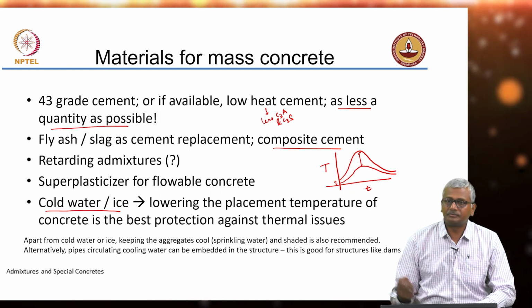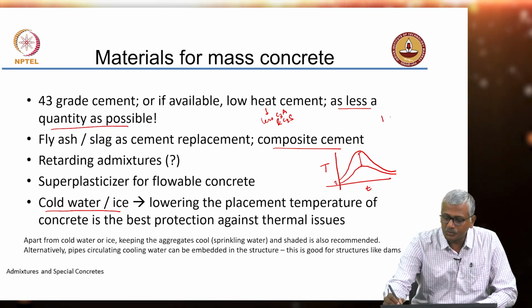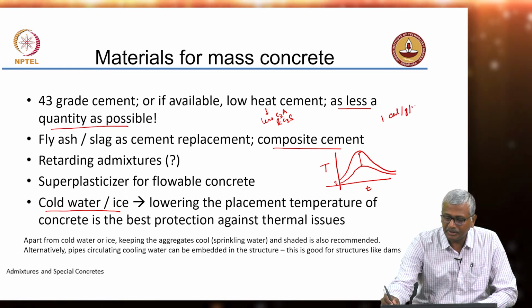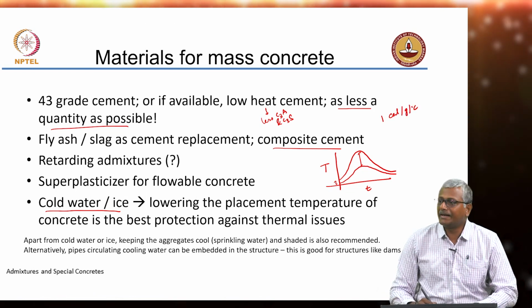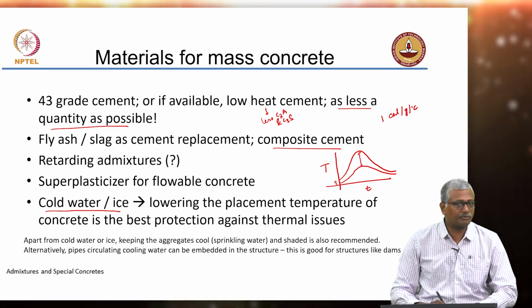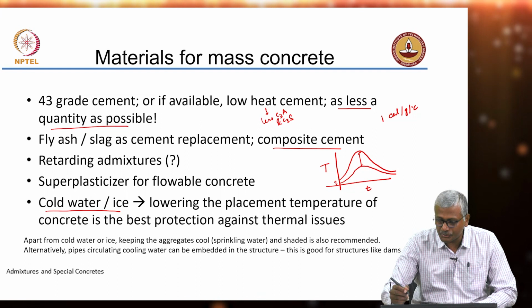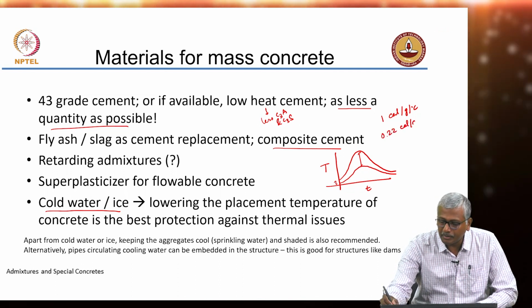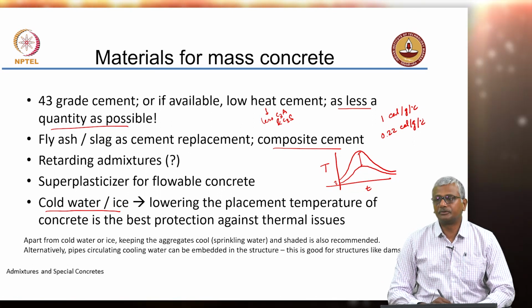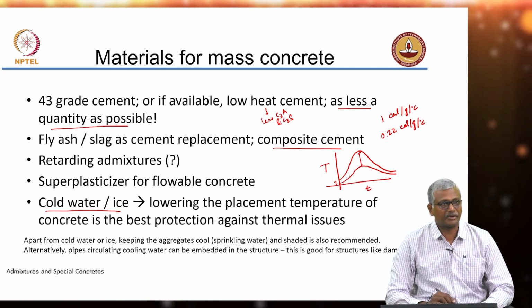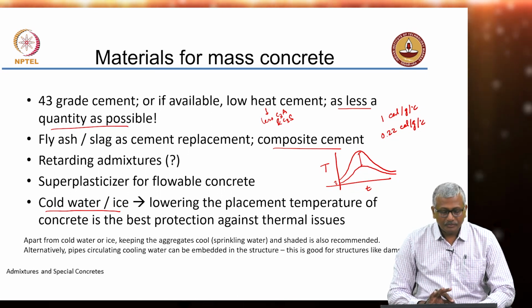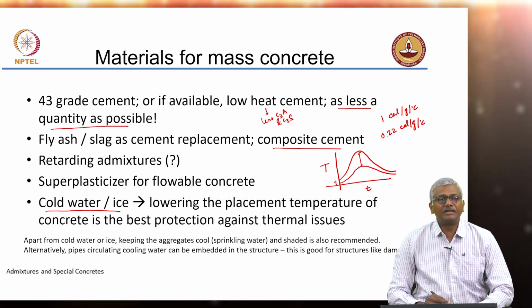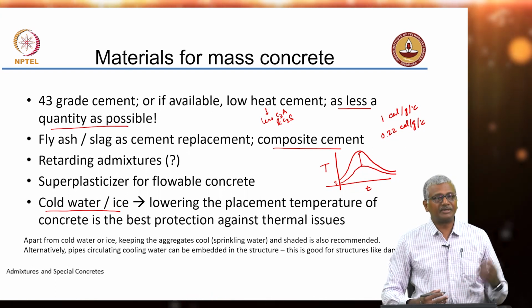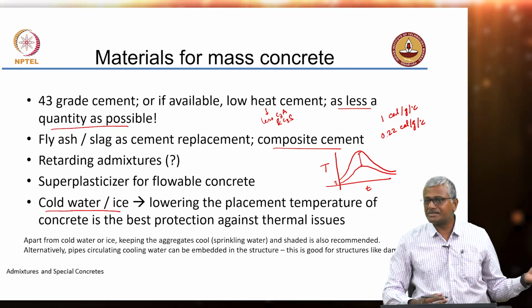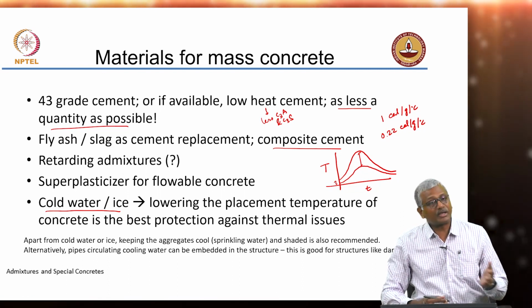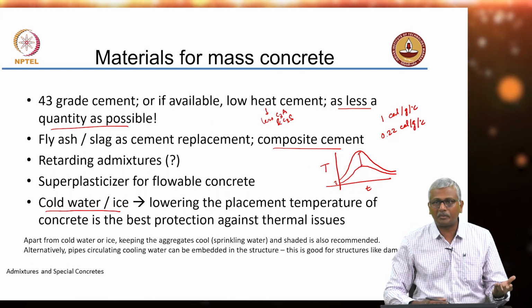So, you remember the specific heat capacity of water is 1 calorie per gram per degree Celsius, right. On the other hand, comparatively the specific heat capacity of your cement and your coarse aggregate and fine aggregate is only about 0.22 cal per gram per degree Celsius. So, it is a major difference in terms of specific heat capacity. Okay. So, nevertheless, we know that when we are operating in conditions of really hot weather, your aggregate and cement are also quite hot. Okay, cement, whatever weather you're operating at, will be hot.